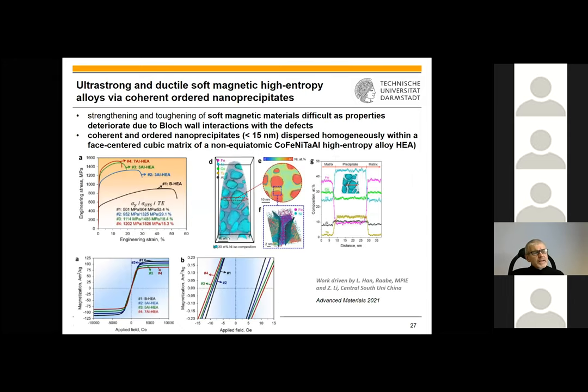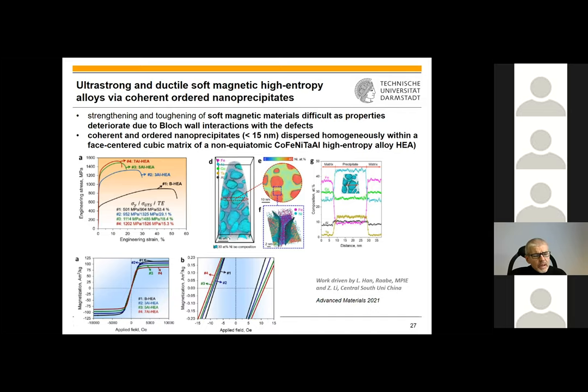And let me, in a last slide, extend a little bit to soft magnets. That is some recent work together with the Dirk Raabe group at Max Planck in Düsseldorf, where we address also the secondary properties like mechanical strength. Here in a high entropy, non-equiatomic high entropy type alloy. And you see these precipitates forming, and the combination of mechanically ultra hard and strong with magnetically ultra soft properties can be achieved here. So that is also something we find very interesting for the future.